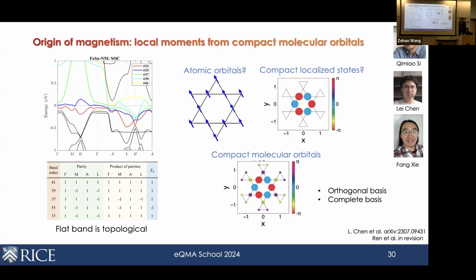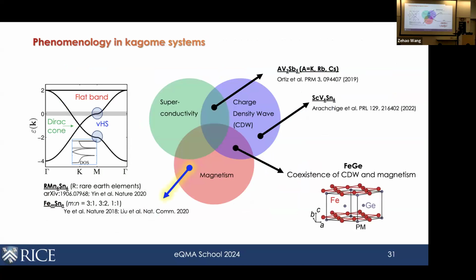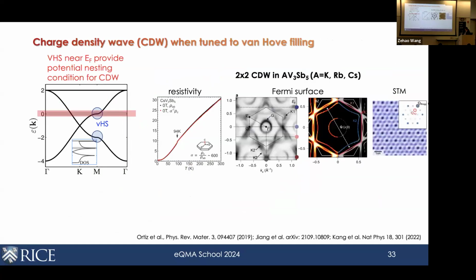Right, so that's the information we've gotten by studying iron tin in terms of what's driving the magnetism in these Kagome systems, even though their flat bands are at the Fermi level. Okay, moving on. Having understood that, we want to next walk over to the region where, besides the same magnetic order, we also start to see a charge density wave order, and that is seen in the iron germanium material. But before I get to iron germanium, I want to say a few words to introduce charge density wave order in the Kagome systems.